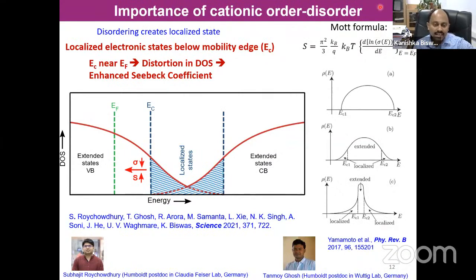So if the mobility edge moves this side, my electrical conductivity decreases, but the Seebeck increases. That means by tuning this mobility edge, or tuning the order or disorder in this compound, I can play around with the electrical conductivity and Seebeck coefficient. That's the motivation we have. So as I told you, the Anderson localized regime is no good for thermoelectrics. We have to work in a regime which is a precursor of the Anderson localization regime, which is nothing but a